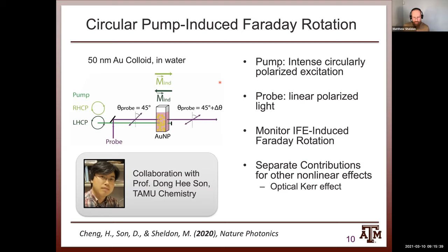So the point of this story is I just wanted to make the claim that this gives rise to really interesting and fundamentally different behaviors in the electronic and physical properties of these nanoparticles. So we did an experiment with one of my collaborators at Texas A&M in the chemistry department. We thought, maybe we can measure the evidence of these magnetic fields in a time-resolved way. So we performed a pump-probe experiment trying to measure this inverse Faraday effect, where we had a pump beam that induced the magnetization in a sample of colloidal nanocrystals with strong plasmonic resonances. Then we probed it with just a linearly polarized beam, and we measured the degree of the magnetization based on the Faraday rotation of the probe beam. But we could do this in a time-resolved way.